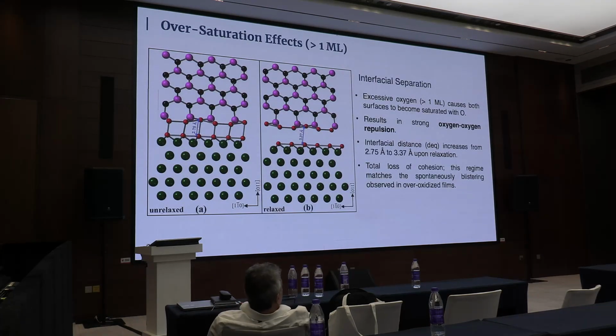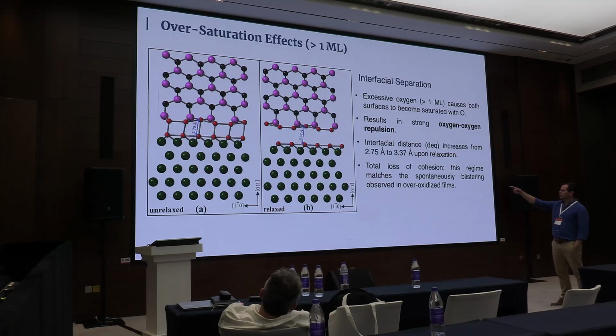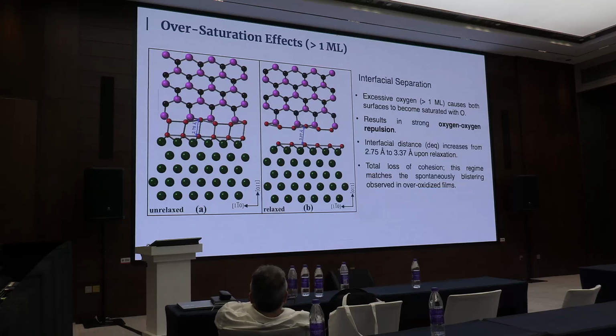Just to make another computation, to be assured that our system explains the situation well, we increase until 2 monolayers, and the physics is a little different because the systems are practically separated by the oxygen. So there could be a spontaneous delamination if we have a lot of oxygen. So even more, if the oxygen keeps increasing, we keep having the same situation, even worse.